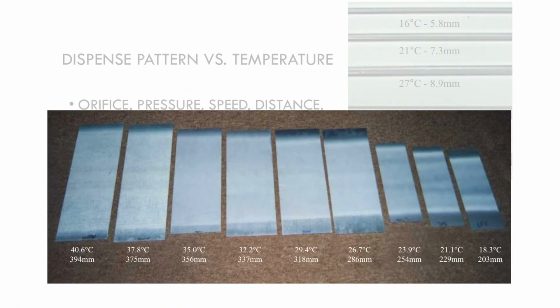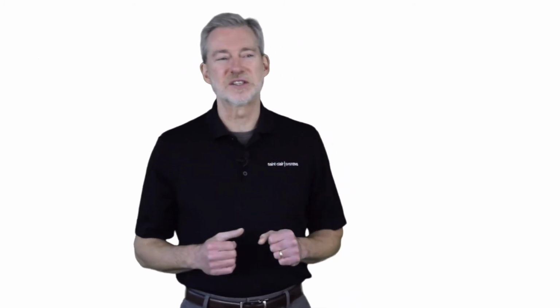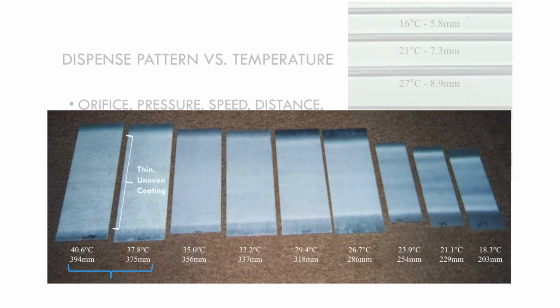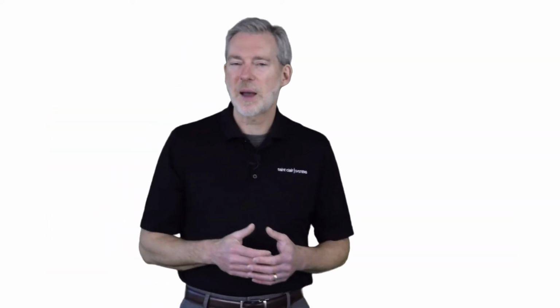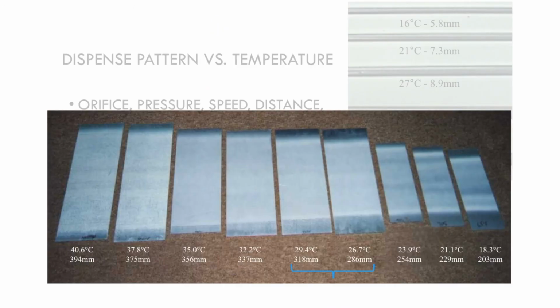Spray applications, like this anti-chip sealer, are similar. Here we can see the impact of temperature on dispense. The most obvious change is in the width of the fan pattern, but perhaps even more important is the impact of viscosity on spray consistency. Above 35 degrees, the coating is thin and uneven. You can see the substrate peeking through, but in the 30 to 35 degrees C range, the coating is smooth from edge to edge. This is probably the optimal operating temperature for this particular process. Below 30 degrees, we see heavy edges beginning to appear, which are often associated with striping on the finished part.